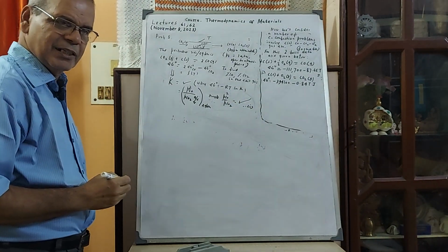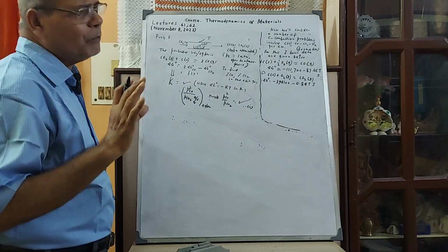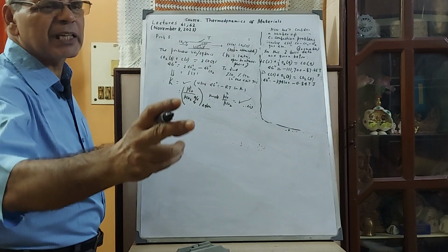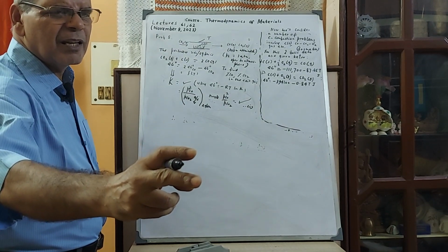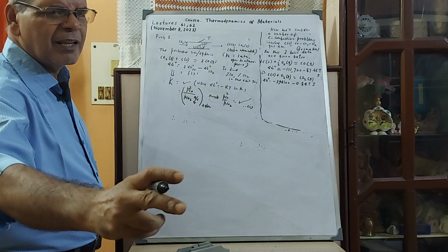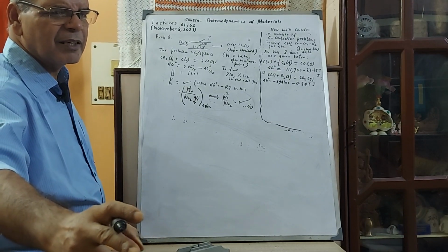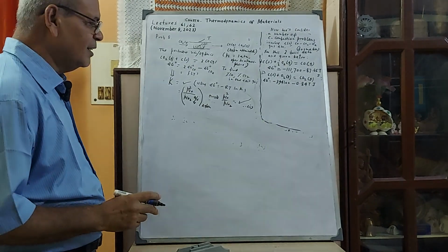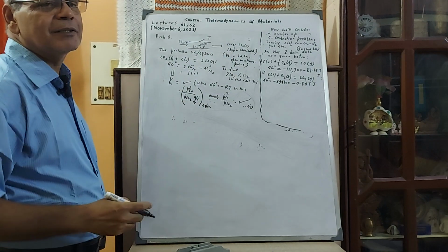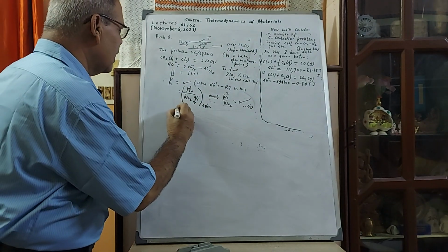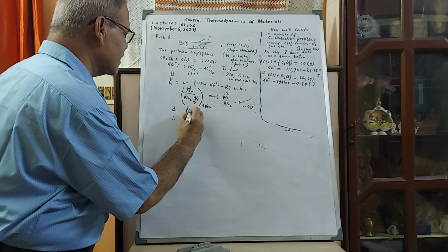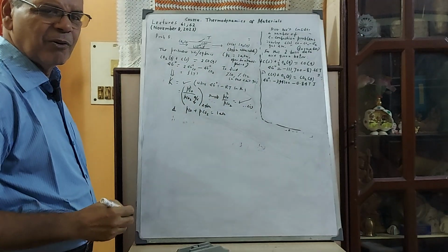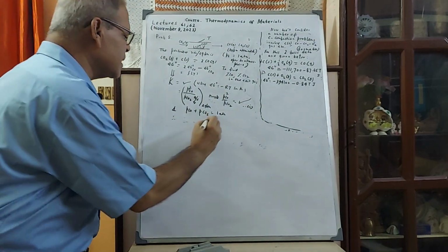Another equation you have to generate, so that you can solve two unknowns with two equations. You follow me. Try at most. What is another one? The partial pressures sum to total pressure, which is 1 atmosphere, open to atmosphere. So PCO plus PCO2 is 1 atmosphere. Can you solve? It is something like y square by x.